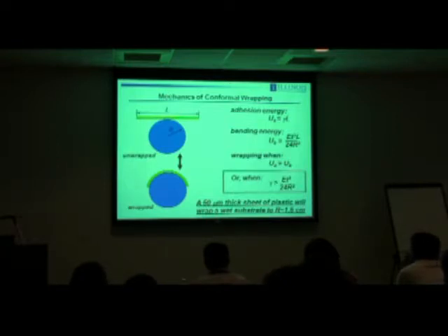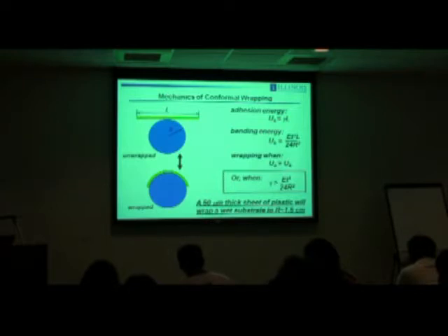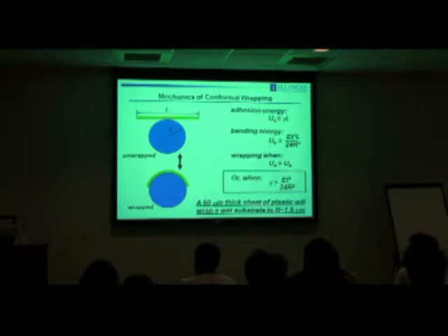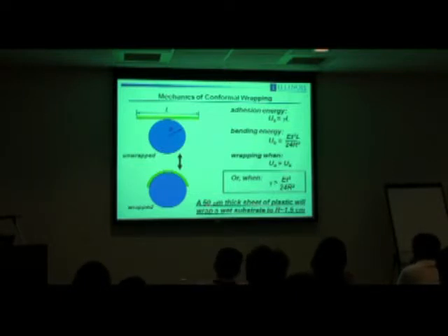So if you want wrapping, you want the bending rigidity as small as possible. You could imagine going to a low modulus material, but you have limited headroom there. You can drive the thickness down. The problem with driving the thickness down to the extreme levels that I showed you before is that the circuit then becomes too floppy to manipulate. The surgeon needs to manipulate it and mount it on the brain. So if it's floppy enough to wrap the brain, it's not self-supporting. It just falls on top of itself. So for a 50 micron thick sheet of plastic, which is a good ballpark number for something that's thick enough to be mechanically manipulated, you can really only wrap a surface with a radius of curvature down to about 1.5 centimeters, even when it's wet. You can't do smaller than that.